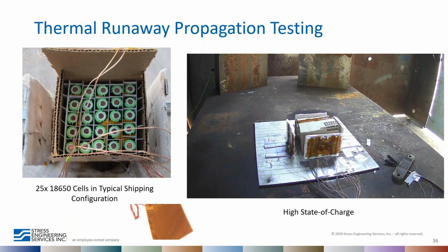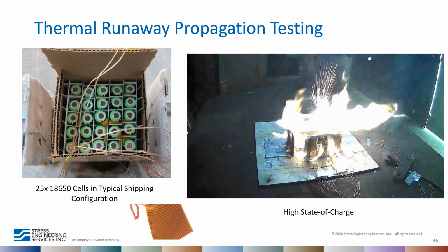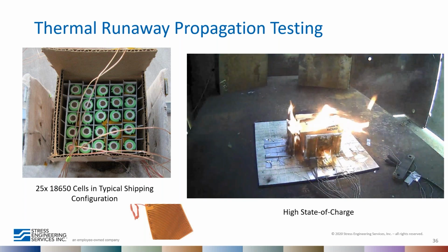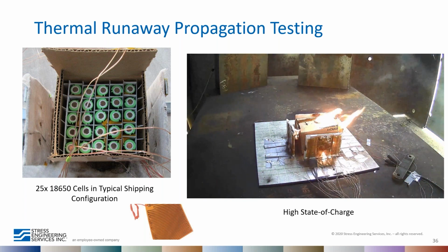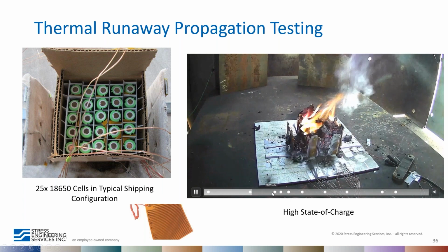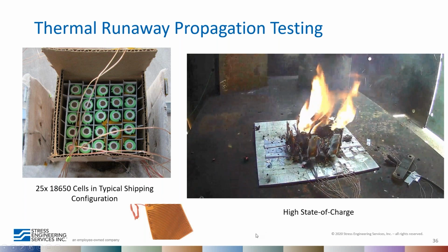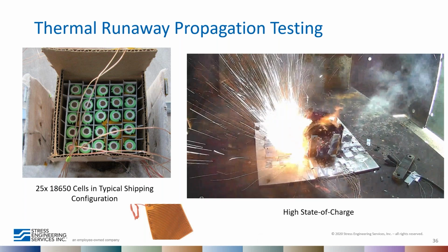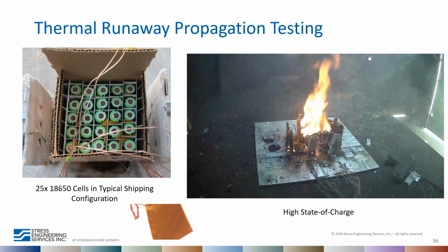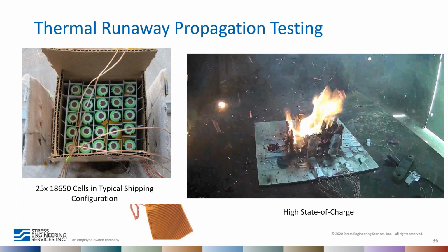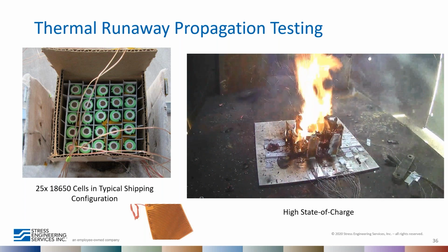So this is one example of a typical shipping configuration of 18650 cells. We're mimicking how these cells are typically transported before they're used to assemble a battery. And what we're doing is we're applying external heat to the center cell using a Kapton heater. And in this case, this is for a battery with a high state of charge. And so if we skip ahead, we start to see thermal runaway reactions in the trigger cell, and then it propagates out to the neighboring cells, causing a release of electrolyte and rapid explosion of the cells.